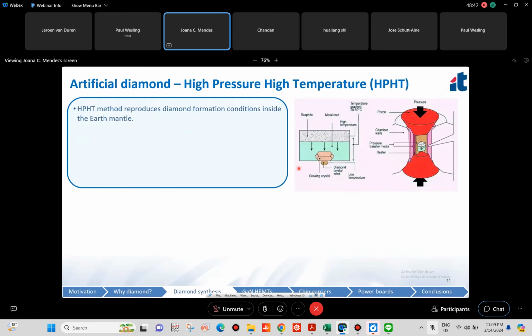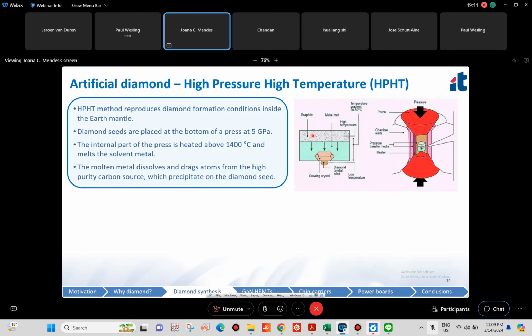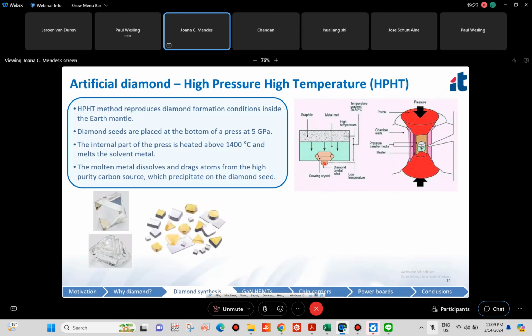And now, to fabricate artificial diamond, we can use the high pressure, high temperature method, where we basically try to reproduce the same conditions that are required inside the earth mantle. So we place the diamond seeds inside or at the bottom of a press at a high pressure of 5 gigapascal, and then we heat the press above 1400 degrees C, and this melts the catalyst, which is a solvent metal here. And when this metal melts, it will dissolve and drag atoms from the graphite carbon source all the way down to the seed crystal where they will precipitate. And in the end, we have nice crystals, which then can be cut and polished.